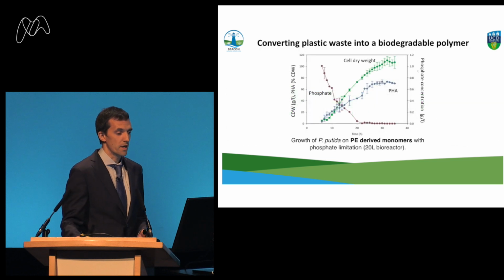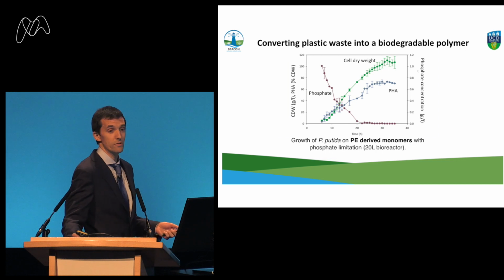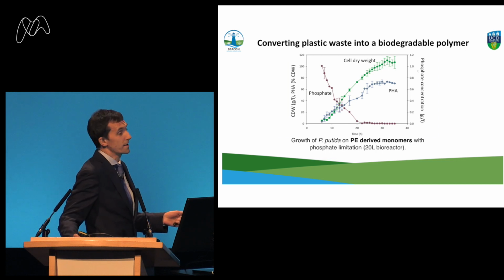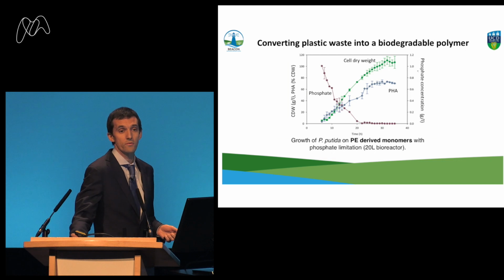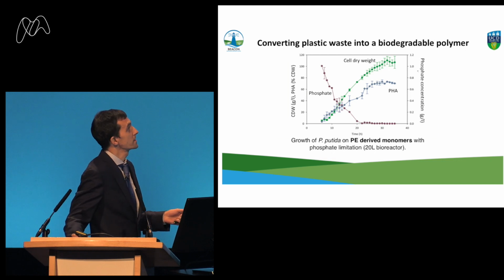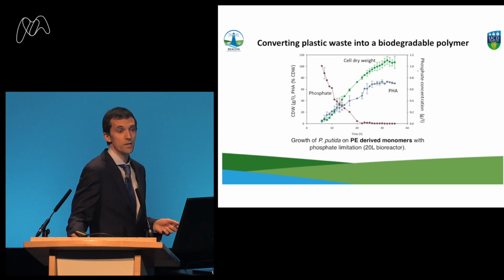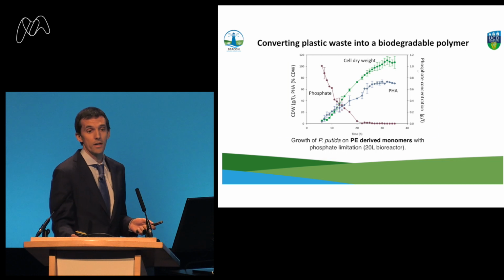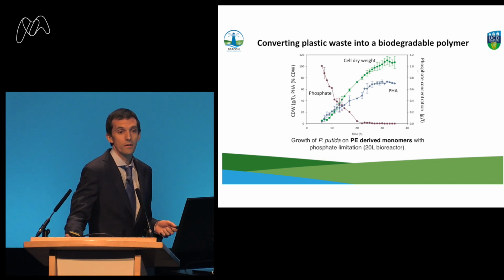So what we did, we first demonstrated that technology, and I'm showing you the best results, of course. I'm showing you here polyethylene-derived monomers. So we took polyethylene, we pyrolyzed it, we actually oxidized it as well, and then fed those monomers to bacteria. And what I'm showing you here is that the bugs start to consume phosphate. It needs an inorganic nutrient, and after about 24 hours, it's undetectable. The bugs are growing, and basically they achieve over 100 grams of dry weight per liter, which is equivalent to about 300 grams of wet weight of cells per liter, which is really high cell density. And 100 is really the target if you want to make it commercially successful. And then they also accumulate PHA, around 65 to 70% of the cell is actually polyhydroxyalkanoate. So these guys are absolutely bursting with polymer.